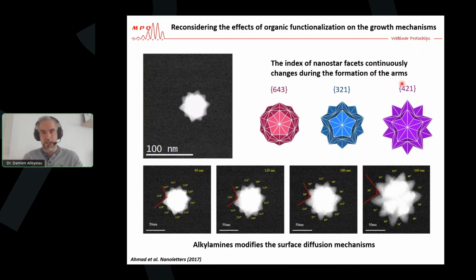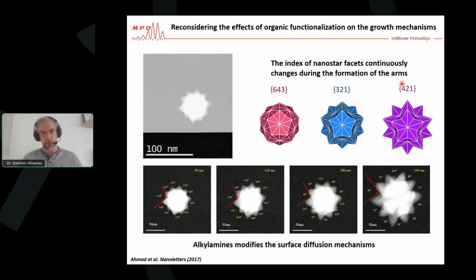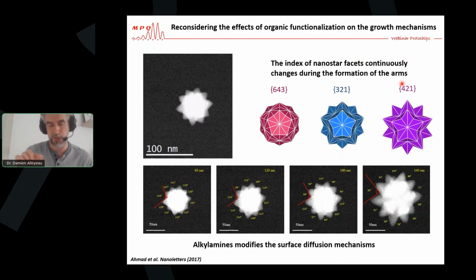So in fact, the effect of functionalization is not a thermodynamic effect. It drastically changes the surface diffusion pathway of atoms to end up in another equilibrium structure. So the whole mechanism is different. So we should stop only looking at the final result of a structure and thinking only in terms of thermodynamic equilibrium. The whole mechanism is different.